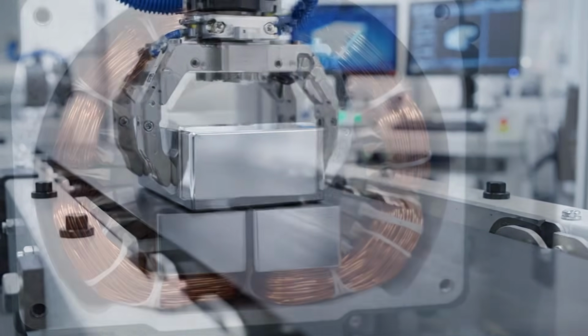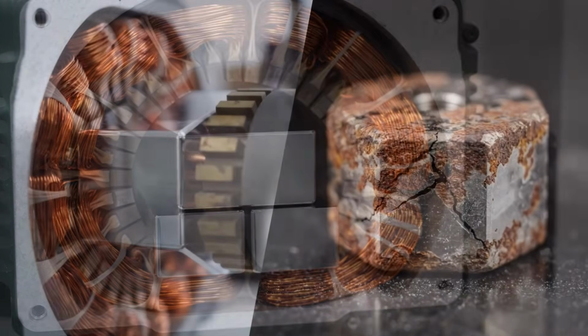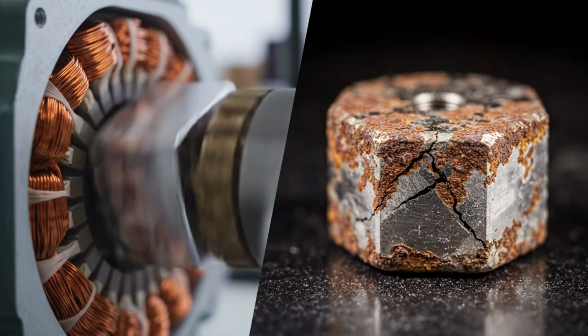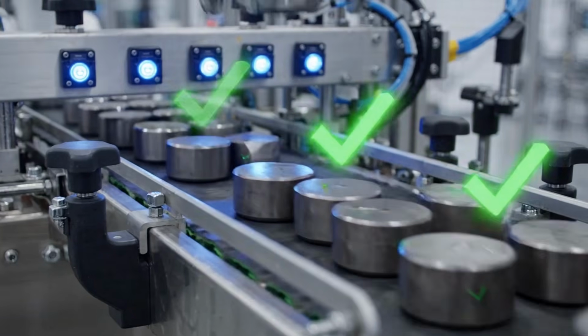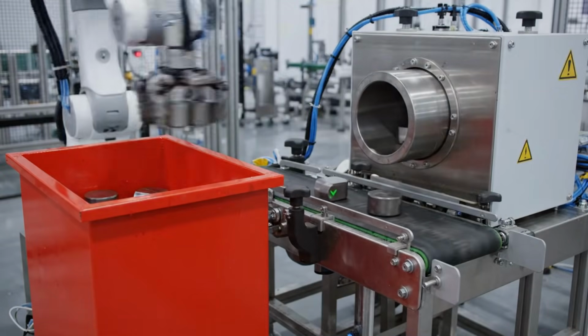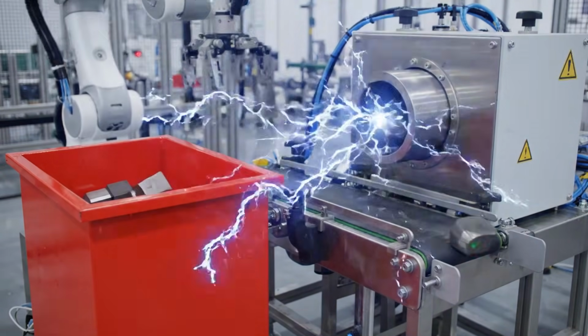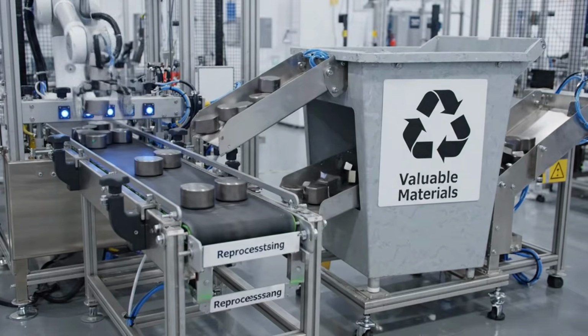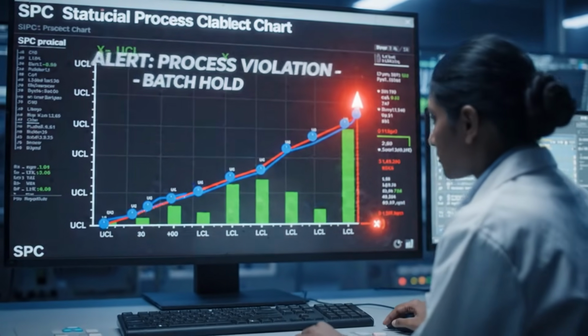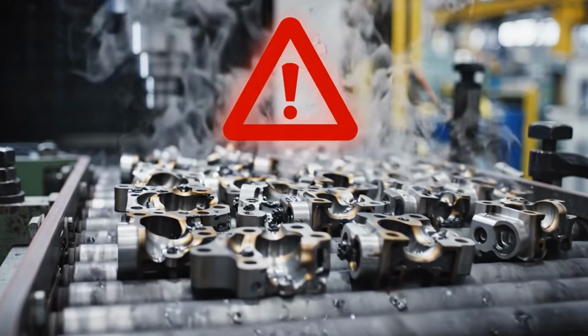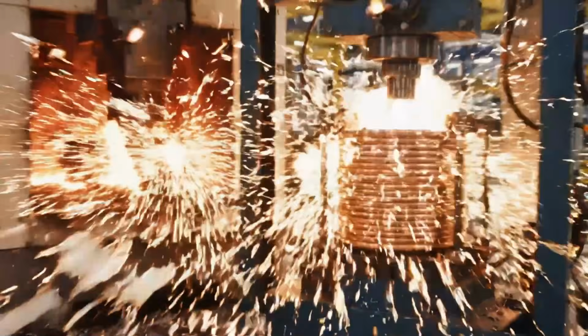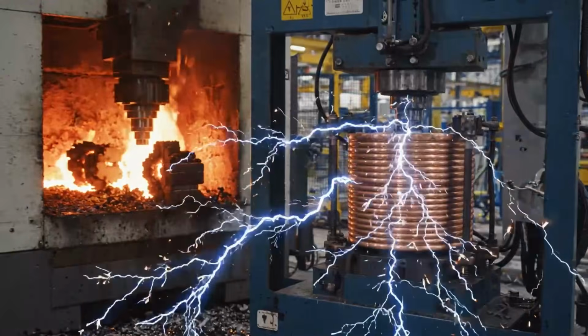Once the raw materials are purified and dosed, the metallurgical transformation begins. In neodymium iron boron magnets, the components are placed in induction furnaces. Before melting, the chamber is evacuated to remove oxygen and moisture. It is then filled with an inert gas, usually argon, to prevent oxidation. This protected atmosphere is vital because the alloy must maintain an extremely clean composition. If oxygen enters during melting, oxides form that weaken the material and reduce the final magnetic strength.